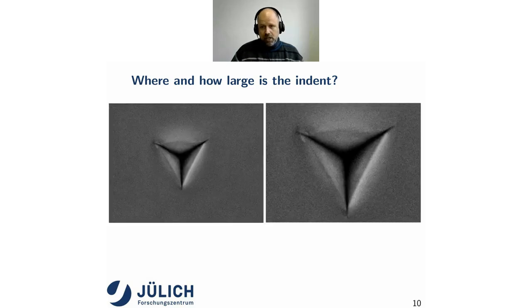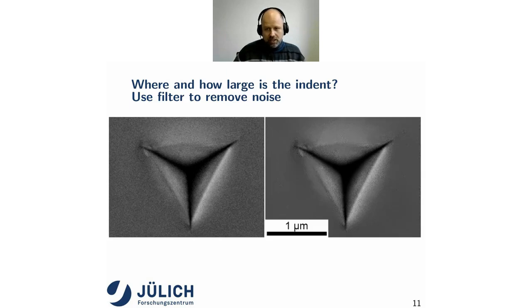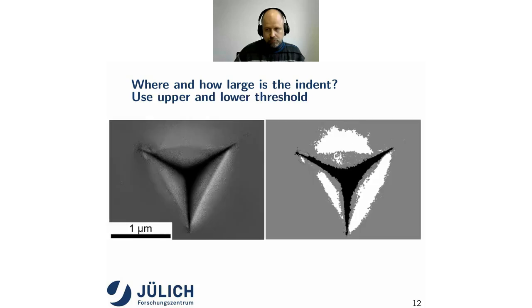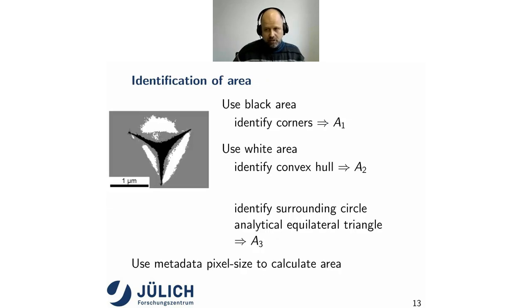The first thing that we do is, if we have an image, we zoom in, right now just for you as the audience to observe it more clearly. Then we clean it up a little bit to get rid of all the noise. This cleaning is definitely easier surrounding the indent than in the area of the indent. Then we can basically threshold it by a lower and upper boundary. So we have basically the black star and the white areas surrounding it. And now we can use this information to determine the contact area.